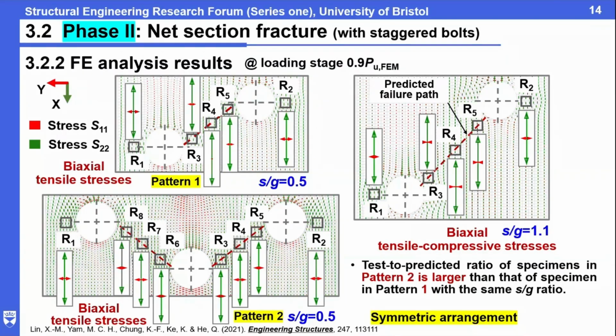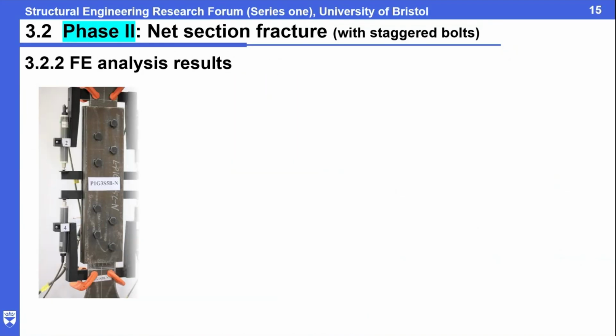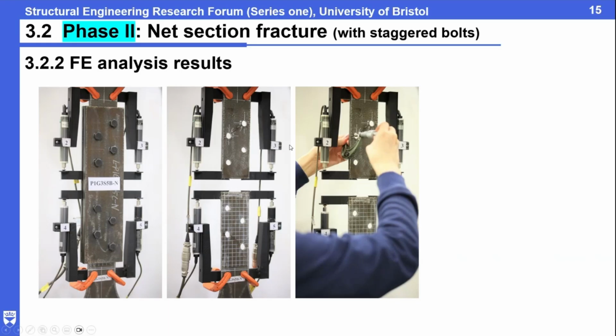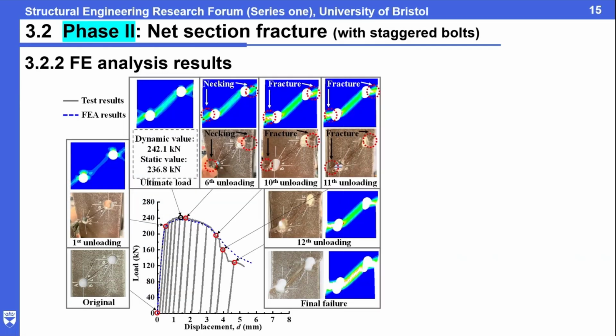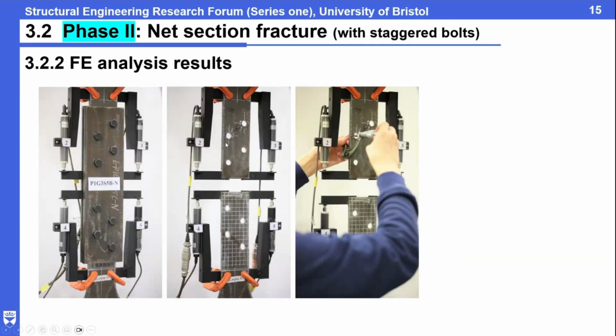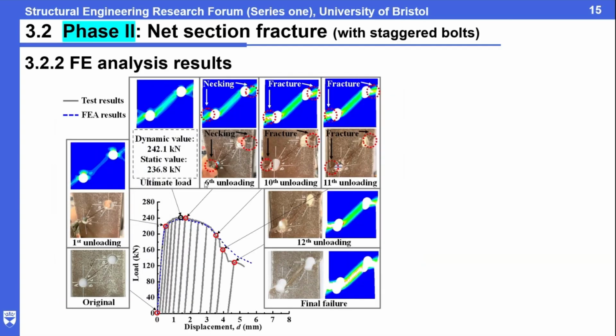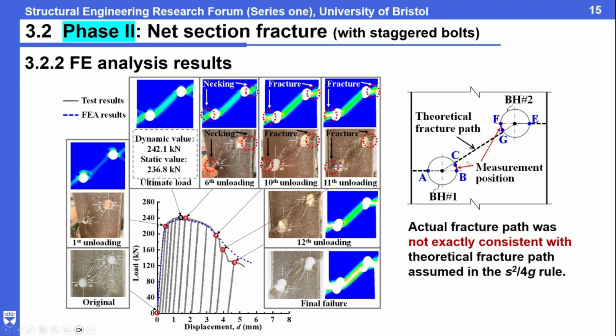And another thing: you remember we mentioned the S²/4G rule, right? For the staggered section, when we calculate the area, we need to use the S²/4G rule. This rule is based on the assumption that the fracture path goes through the center of the boreholes. We wanted to look further at whether the development of the fracture path actually follows this kind of path. We loaded, then unloaded to open the cover plate to check how the fracture path develops. Combined with the test and the numerical model, we found that the fracture actually does not just occur on the linking line.